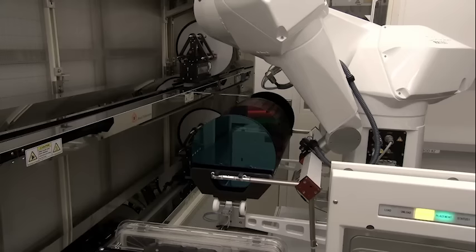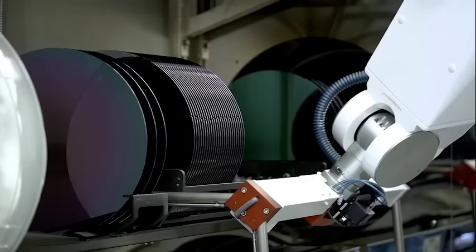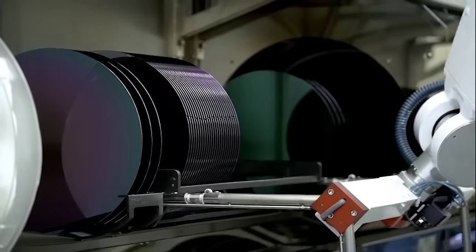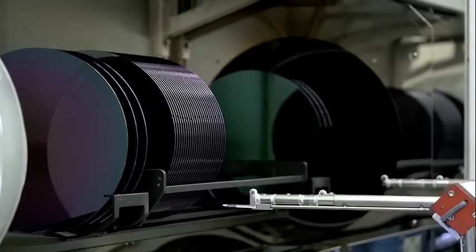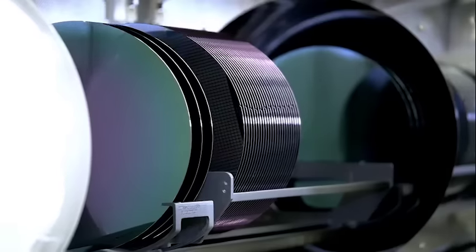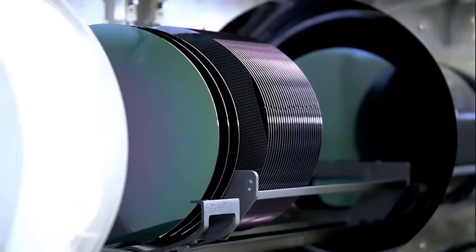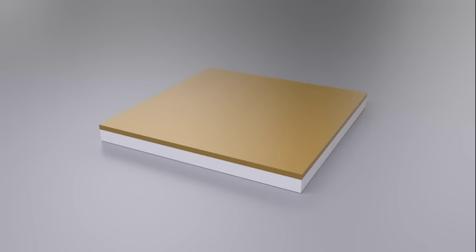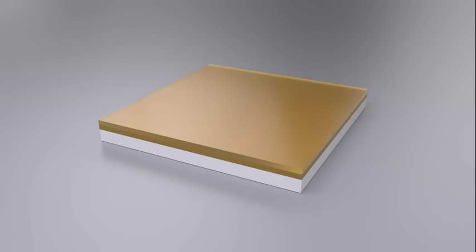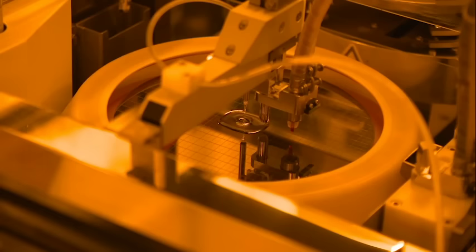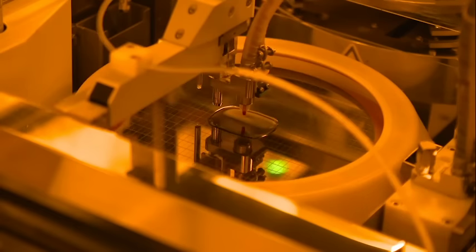First of all, the surface of the wafer is oxidized in a high temperature furnace operating at approximately one thousand degrees Celsius to create a non-conductive layer. Then a photoresist material is uniformly distributed on this non-conductive layer using centrifugal force. This coating process creates a light-sensitive layer.